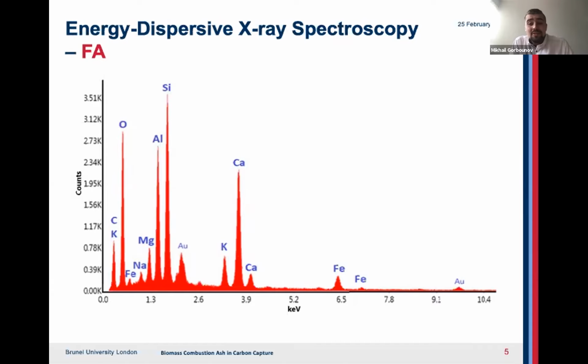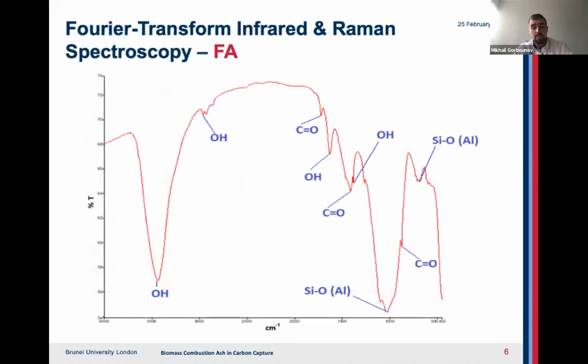Apart from that, the main constituents of this potential adsorbent are alkali and alkali earth metals, such as sodium, potassium, magnesium, and calcium, with potassium and calcium being most prevalent across the conducted tests, as well as some iron and carbon. Gold can also be clearly identified from the scan. However, the fly ash sample has been covered in gold coating by a sputtering technique prior to analysis in order to negate any possible charging.